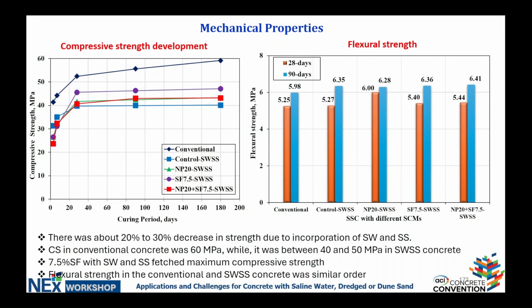This gives you an idea of what is the compressive strength. So if you look at the diagram on the left, you can really see that in the case of the mixture that we study, there is definitely a difference between, let's say, what we call the conventional and then the mixture with seawater and sea sand. And one of the findings, and this is being investigated as we speak, is really a weakness at the interface between the aggregates and the cementitious paste. And this is more than the seawater, is really an issue probably due to the sea sand. And so this is an item that is being investigated, and some of the SCM work that is being done now will shed some light on it. What is interesting is that the flexural strength has not really changed. So the ability of the material to perform under tensile stresses is apparently not affected by this weakness at the interface.